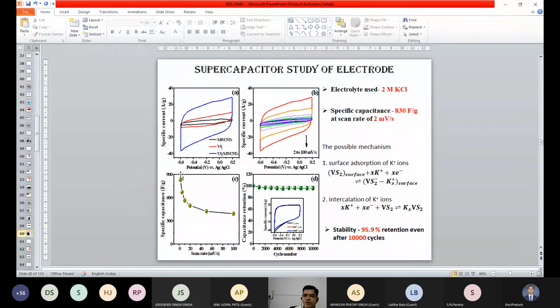And here you can see that the specific capacitance reached 830 farad per gram at 2 millivolt per second. And this is the reduction oxidation kinetics. And we have checked the stability up to 10,000 cycles. Just imagine, 10,000 cycles repeatedly, charging, discharging, that is the CV cycle, up to 10,000 cycles. And you can see that it is more than 95% stability. And it is very stable up to the 10,000 cycles. And that is the beauty of this vanadium sulfide.